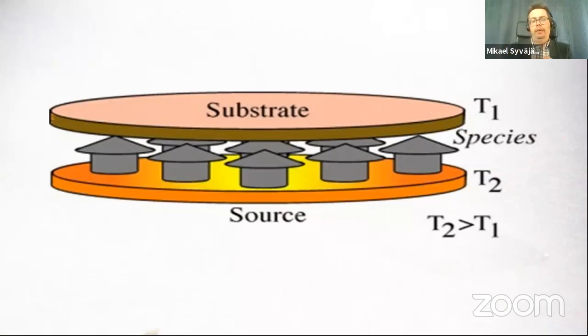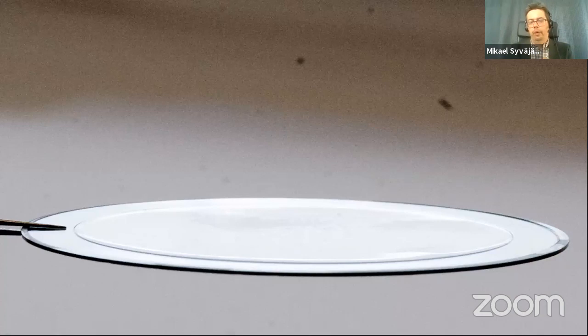And in my PhD, we modified the method. Instead of a long distance from the source to the growing material, we decreased it, but then we could use the growth rate and we can make an epitaxial method to make thin films, which actually were thick films for the silicon carbide, because to convert 10,000 volt in the power devices, you need thick film. So that was the aim of this method and my PhD thesis, to develop it further to make thick films on silicon carbide substrates. And here is an illustration of a wafer with a film on top of it. So we managed to develop the process to achieve the growth and thick films.